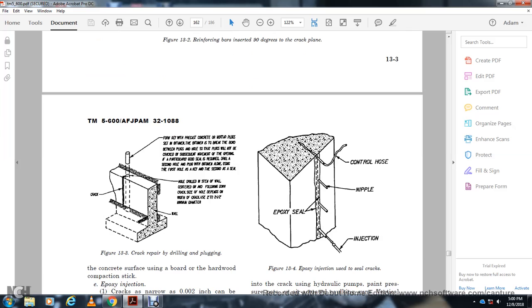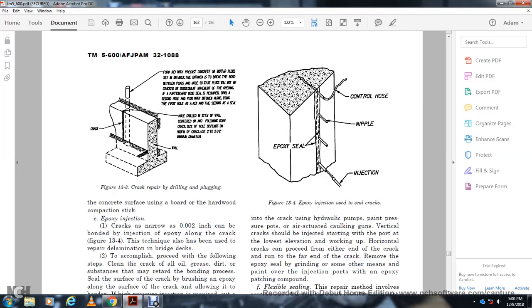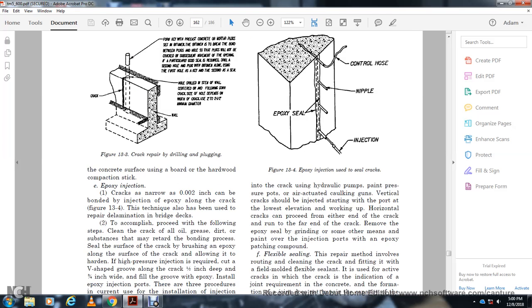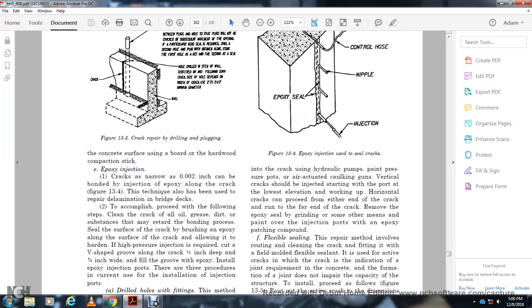Figure 13-3 shows the cracking, drilling, and plugging, and then 13-4 shows the epoxy injection using sealed cracks, control hose, and nipple injection of epoxy. On the concrete surface, a crack narrow as 2,000ths of an inch can be bonded with injection epoxy along the crack. The technique has also been used for repair of delamination of bridge decks.